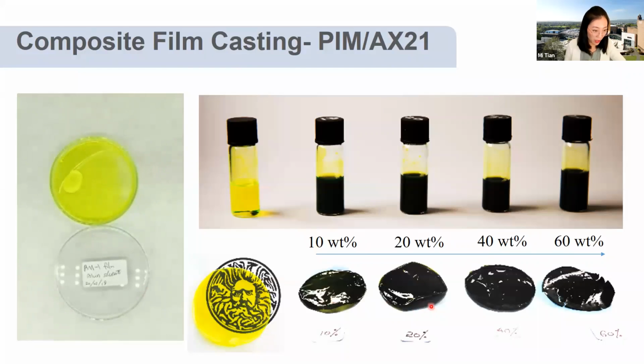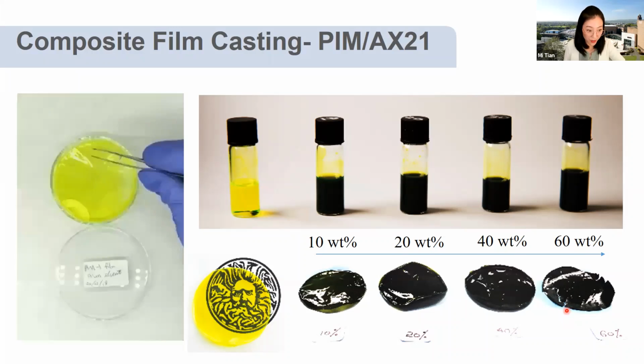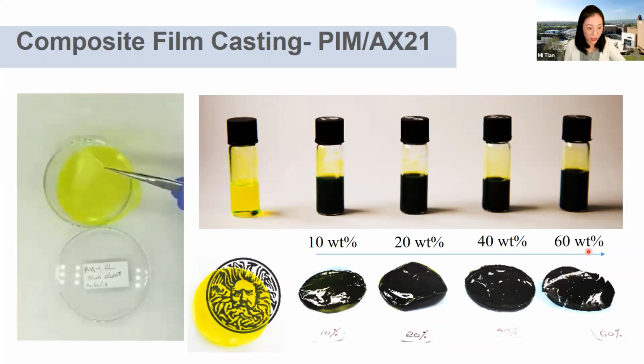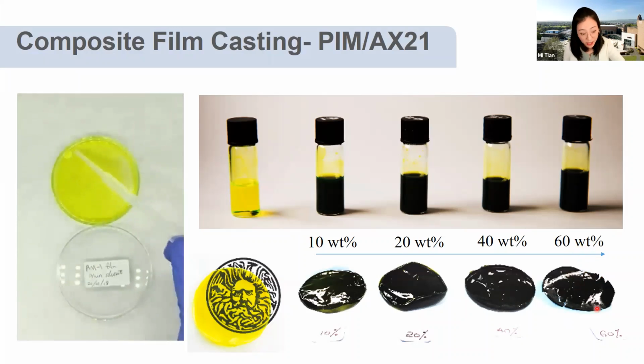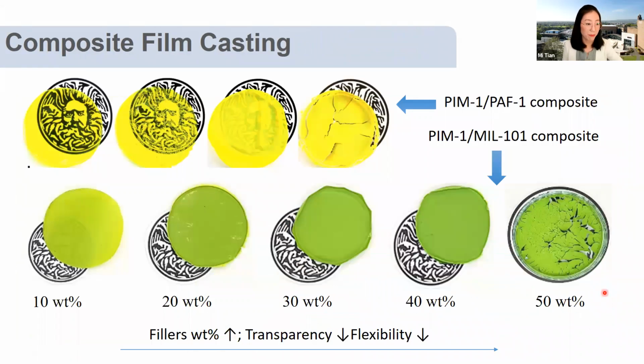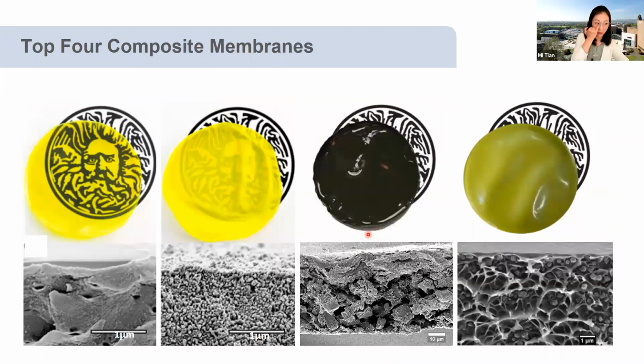So those are the films we manufactured. These are pure PIM1, and these are composite films. And a really good thing is we can add quite a lot of polymer porous fillers inside. The maximum concentration is about 60 weight%. But you can see that at 60 weight% it is already brittle, very difficult to hold its shape. So those are different composite membranes, and basically with the increase of filler concentration, the transparency decreases and the flexibility also decreases. So those are the top 4 composite membranes.